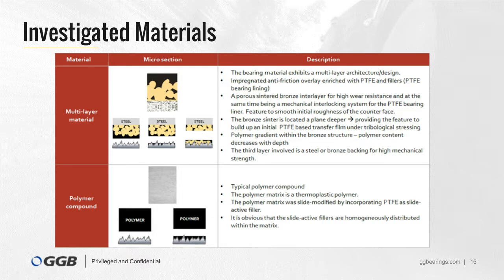On one side, we have the metal polymer composite. This material is heterogeneous with a multi-layer architecture. Starting with the metal backing for high mechanical strength, we have a porous sinter structure which provides high wear resistance and, at the same time, acts as a mechanical interlocking system for the slide active bearing liner. The bearing liner is normally composed of PTFE plus other fillers.